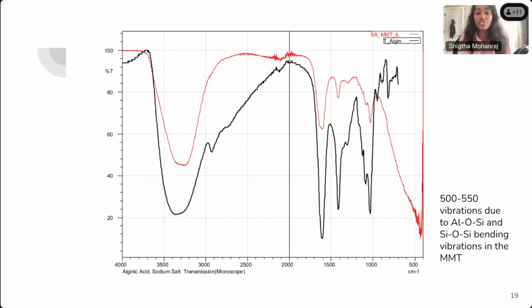And then I also compared the sodium alginate, montmorillonite, and ionic liquid compound to alginic acid. And we can see that there are a lot of characteristic curves found in common between the two, confirming the presence of alginic acid. But there is a lot of variation towards the 500 to 550 range, which is on the far right. But past research has shown that this is pretty characteristic of MMT because of specific bending vibrations. And so this also confirmed the presence of the MMT within the compound.